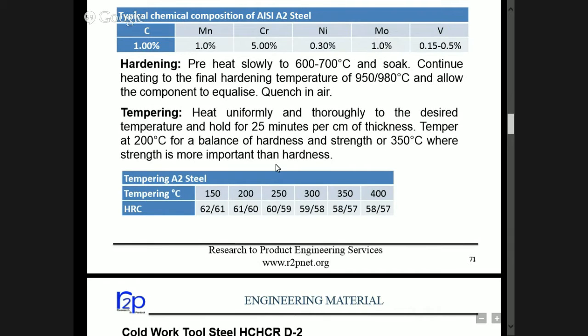So as I explained to you, the tempering temperature defines the final hardness of the component that we will achieve. Like in this table, it's shown if the tempering temperature varies from 150 to 400 degrees centigrade, the HRC hardness is reducing. So we have to finally balance the tempering temperature, because in any case the toughness is to come by tempering.